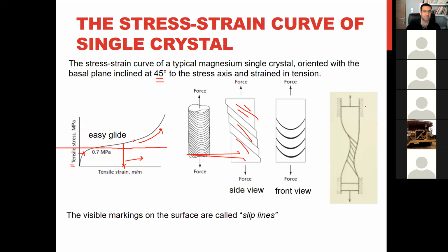We put samples between the two fixtures, grips, like this and here, and the equipment we have for doing such a test doesn't move horizontally. Just this fixture moves up and pulls out the sample. Okay. And here you will see, when you have deformation and you are making a step here, it means the sample cannot keep this angle if you are making these steps. Okay. And this part of the sample will lose this angle.